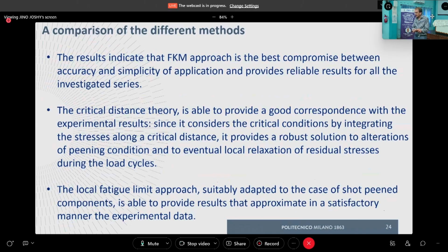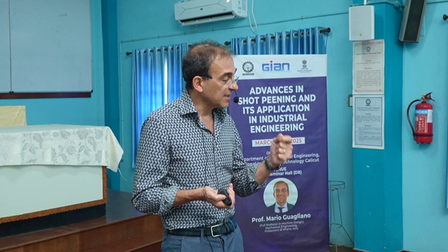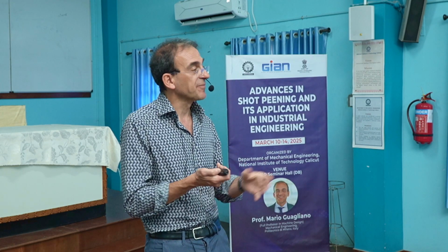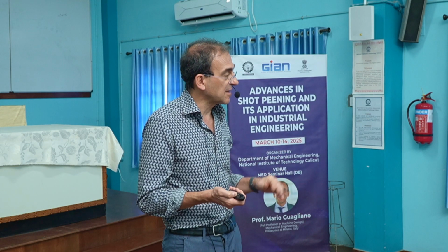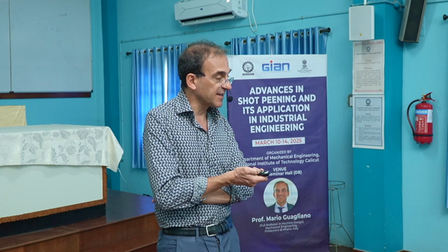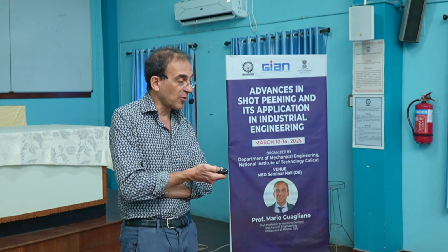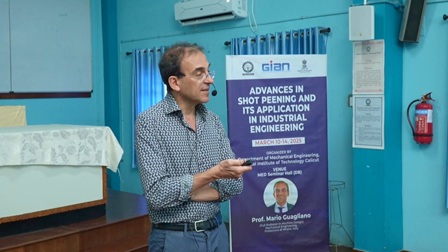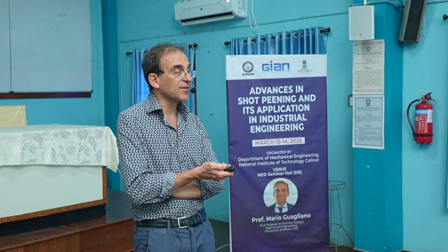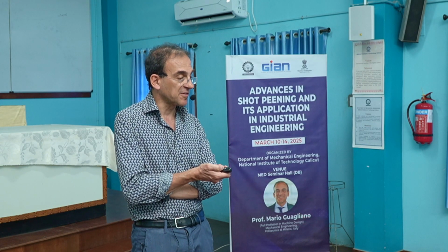The local fatigue limit approach, after the adaptation by means of the coefficient I mentioned in the previous slide, is able to provide accurate results. But these parameters were good for our test, for making good results, but cannot be generalized at all. So if you are using a local fatigue limit approach, it's better to consider some extra experiments to correctly address the factors that are not directly considered in the original formulas of the approach itself.